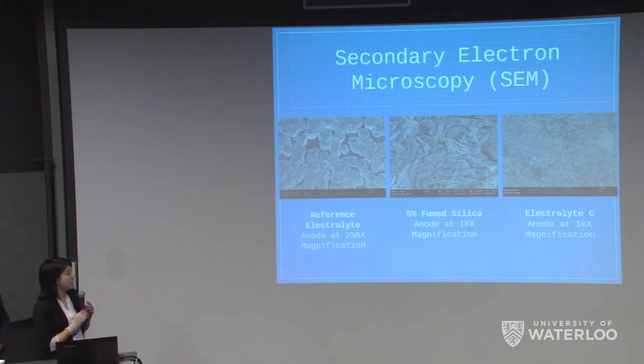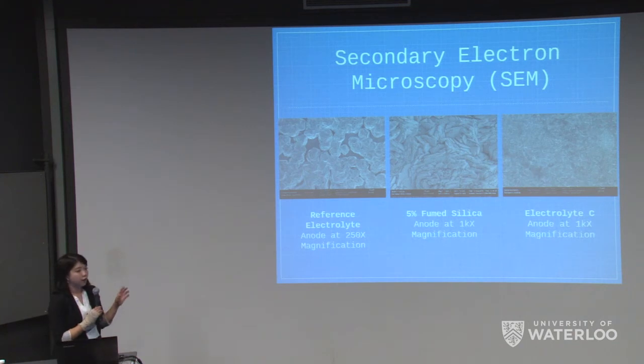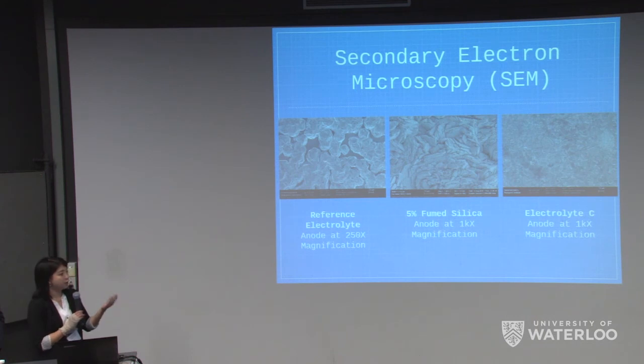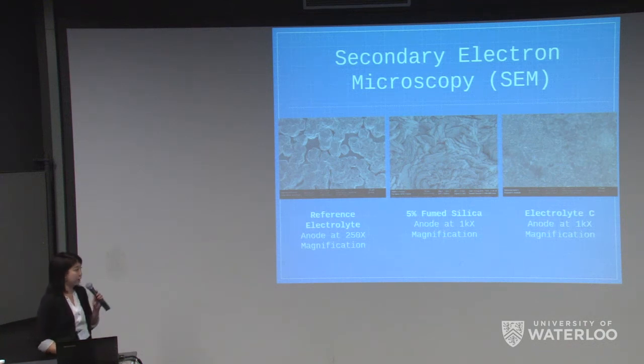And even at such a low magnification, you can see that the dendrites are quite large and they form island-like shapes. These island-like dendrites tend to protrude off of the surface normal to the plane of the anode, directly connecting to the cathode. This type of growth will be very fast and cause short-circuiting at a much faster rate compared to the other ones.